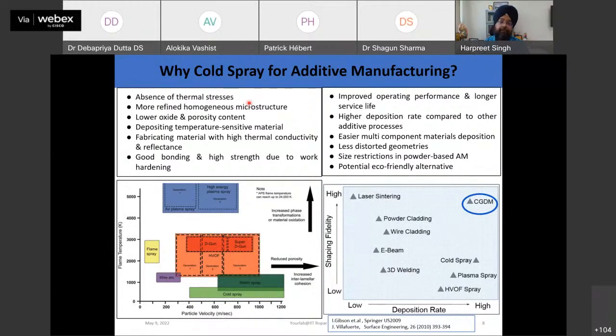But the beauty of cold spray is that there are no thermal stresses. Why? Because we are not melting the powders here. It's a solid state process, which means that you are not going to melt the particles, rather you are pushing them with very high velocity towards the substrate where they deform. There's a lot of discussion on that, but time is so limited that I can't explain it. So in that case, we are not facing any kind of thermal stresses, rather the material is being pushed with very high velocity and it is deforming on the surface.